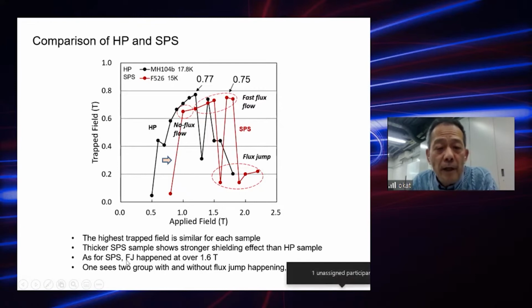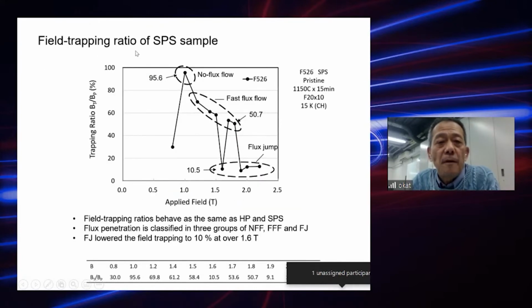That means the red points shifted onto the higher side of the field application. As for SPS, flux jump happened at over 1.6 Tesla in this region. So this is quite a little bit higher field in comparison with the HP sample. One sees two groups with and without flux jump happened as well. So the total tendency is not different as well.